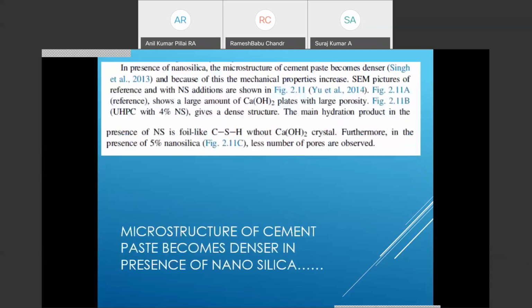is needed. In presence of nanosilica, the microstructure of the cement paste becomes denser, and it enables good particle packing. The microstructure of the cement paste becomes denser, and because of this mechanical properties increase. Some pictures show large amount of calcium hydroxide plates with large porosity, and for 4% nanosilica with ultra high performance concrete, it gives a dense structure.